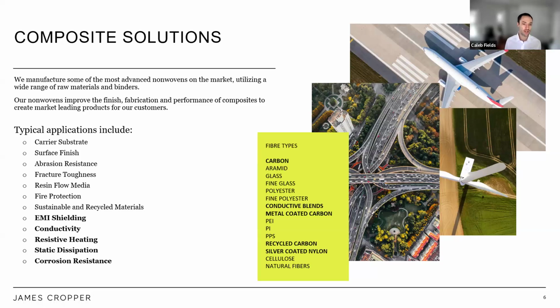So for folks working in composites, our materials, specifically the non-wovens, are typically providing a non-structural function to the composite layup. So within composites, those can be used as carriers, typically for an adhesive. Most commercial airplanes have our materials on them as an adhesive carrier. We also work quite extensively in improving the surface finish of composites, as well as the abrasion resistance, fracture toughness in carbon epoxy composites, fire protection, and we're also working in sustainable and recycled materials such as jute and PA11s as well.